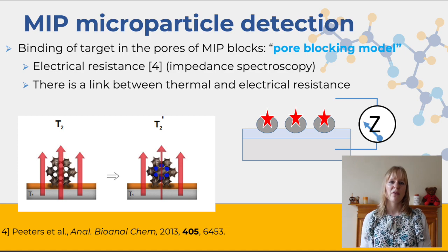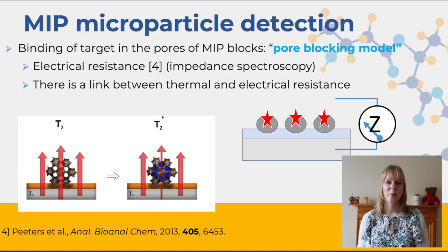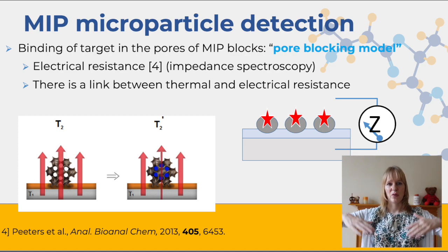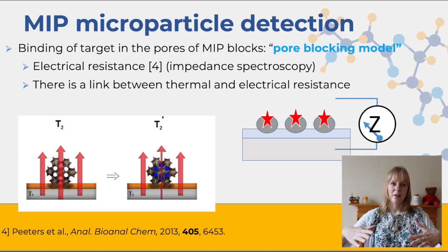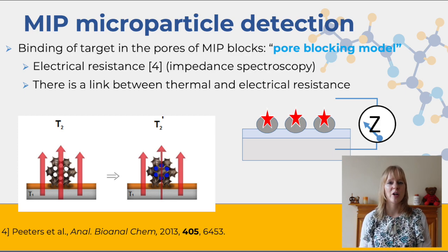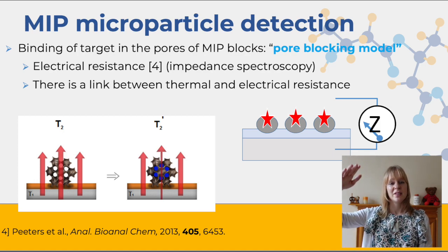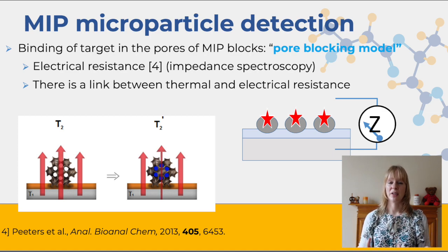Now, what we found out is that it's not just the electrical resistance. We also thought that we could perhaps transfer this to thermal resistance. So other researchers in my group looked at this and applied it to other principles. I found that if I used my microparticles that were designed for neurotransmitters and contain these cavities, and applied a temperature pulse through these materials, you would see a difference between when they're unoccupied, so when none of the target is present, and as soon as some of these neurotransmitters bound to your particles, you could see that the heat flow was blocked, which led to a change in the temperature.